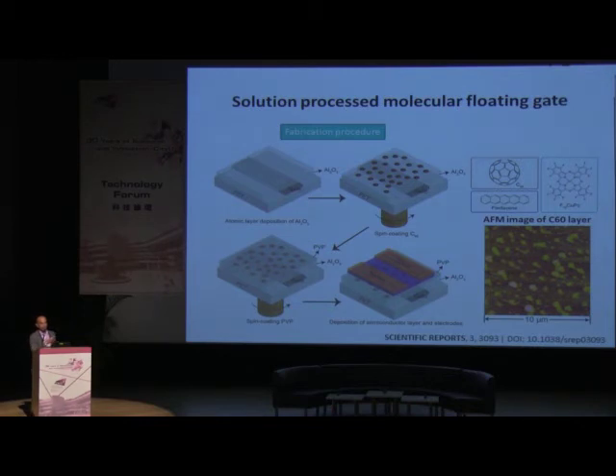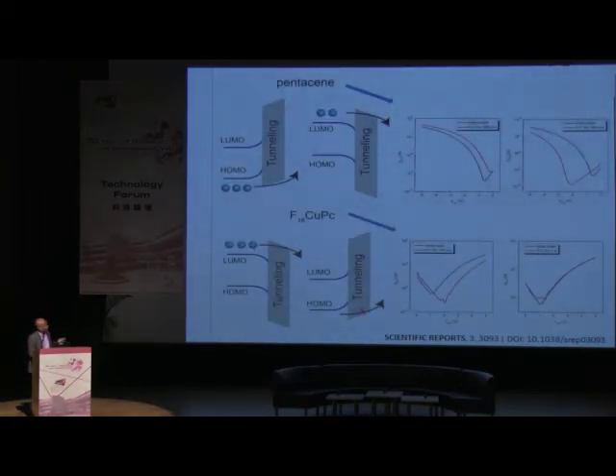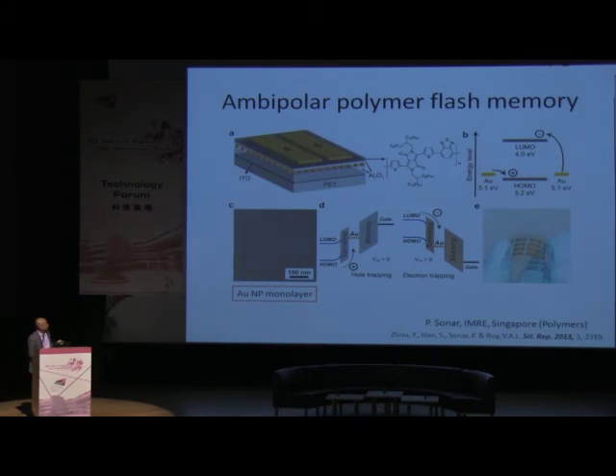Now, in addition, we also made some molecular semiconducting devices where you simply spin coat a layer of carbon-60, which is a molecular semiconductor, but it can form a trapping site to trap those charges. And it can work in both N-type and P-type mode. And in addition, we also put a polymer layer which has both electron and hole transporting capability. It's a kind of balanced transport.